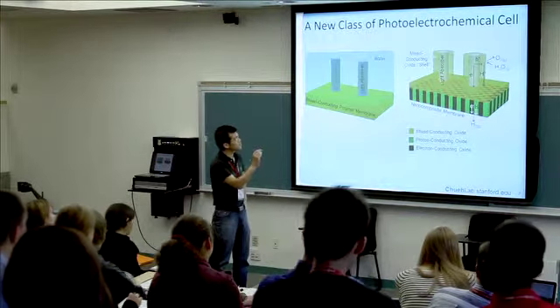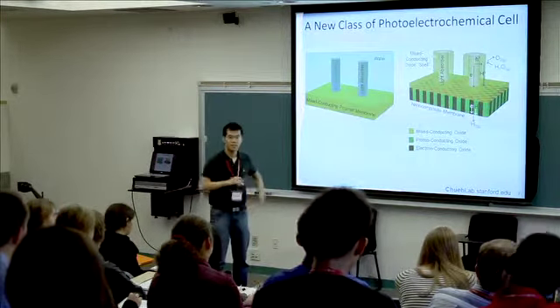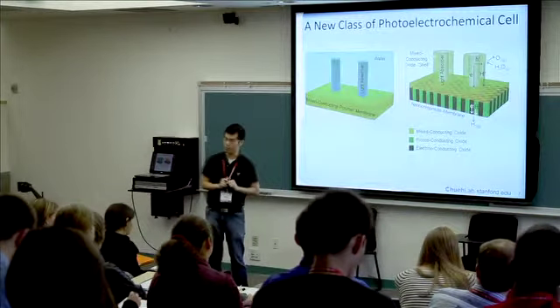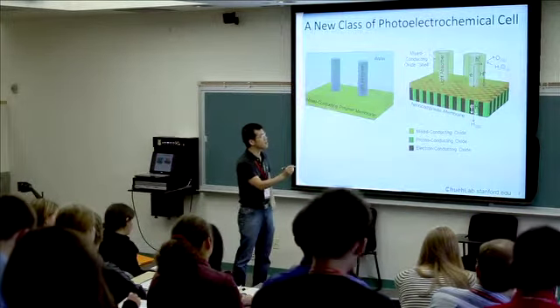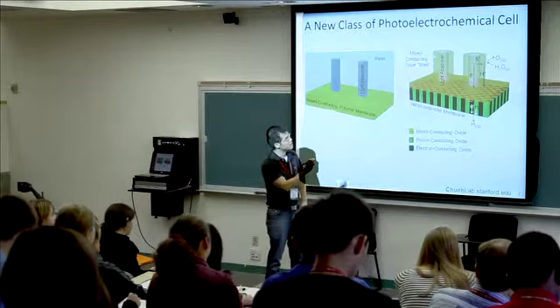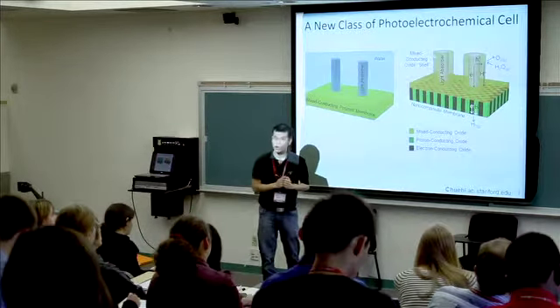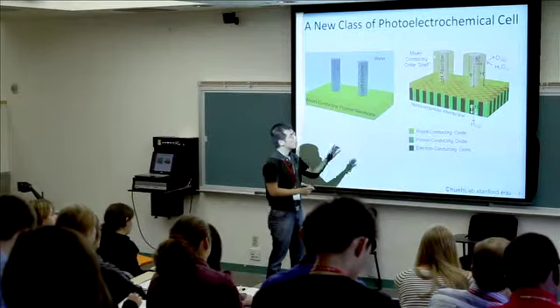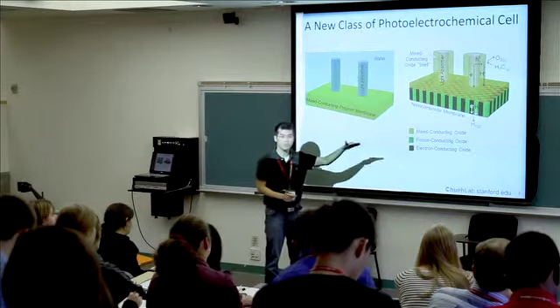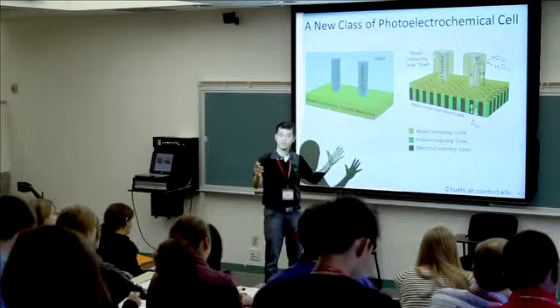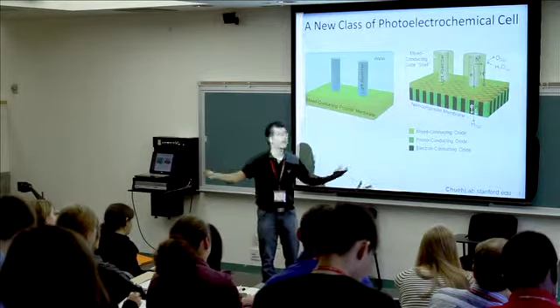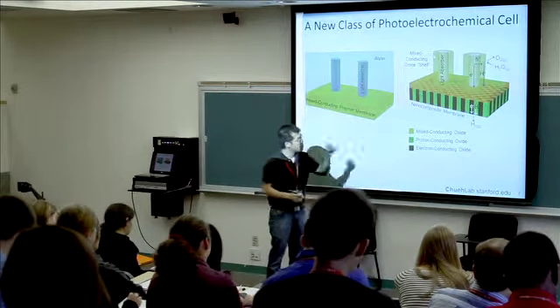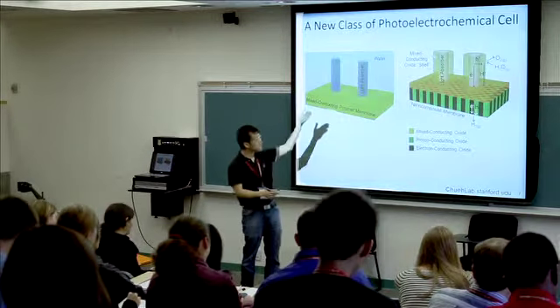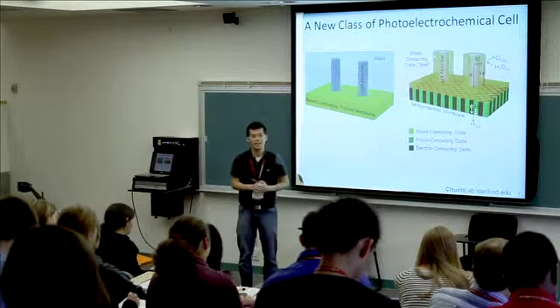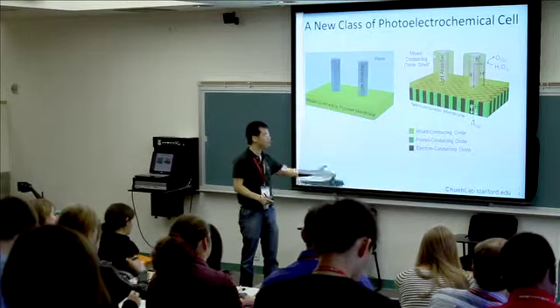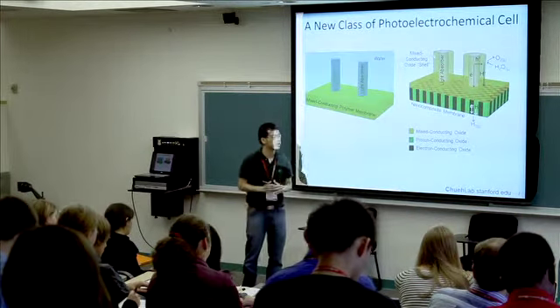You can see here, we still have the same light absorber just like the left side, but now it's being coated with a film of something else, what we call a mixed conducting oxide. So if you follow the reaction that occurs here, you shine light, you form an electron hole pair. This electron hole pair, the hole travels very quickly through this material and reaches the gas. So this is the steam that's outside at several hundred degrees Celsius. And then the chemical reactions occur at the surface and you guide the proton down along the thickness of the shell across the membrane to the other side where hydrogen comes out.